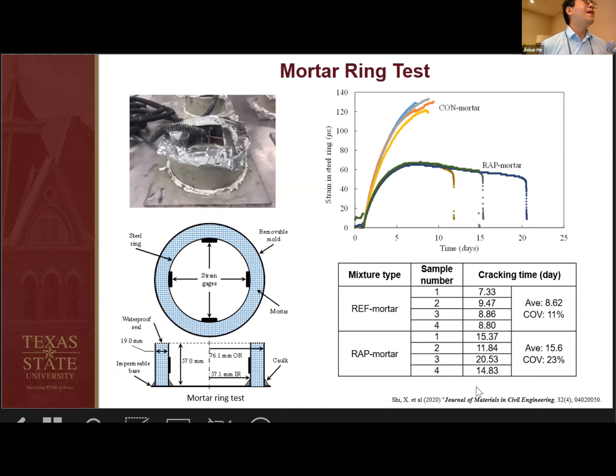Then we also did a ring test. We did a mortar ring test and a concrete ring test. For the mortar ring test, as you can see, by adding RAP you can significantly improve the cracking time, delay the cracking time. So the behavior of the RAP mortar is significantly different from the control mortar. You have a lot of stress relaxation and a lot of creep, also due to lower modulus. Essentially the cracking time of the RAP mortar is about double that of the virgin mortar we tested.